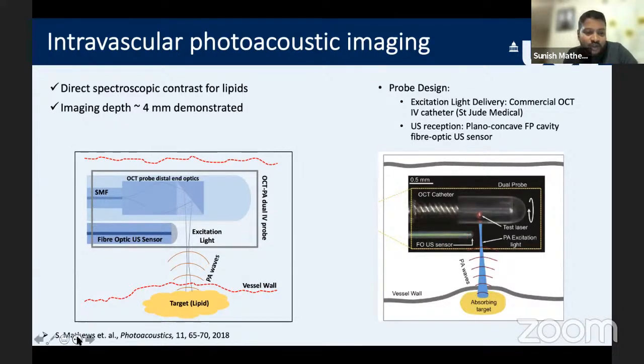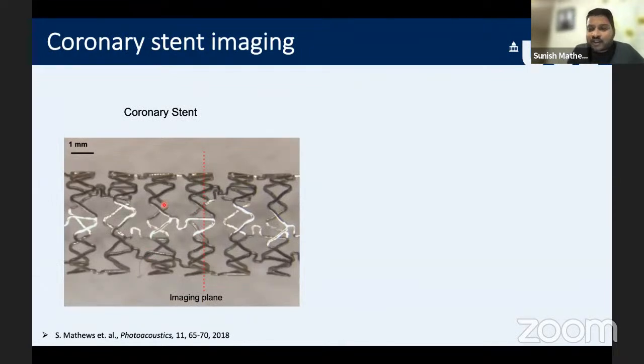Now, let me show you some of the images here. To test our fiber optic probe, we tried to image a coronary stent. This is the image of a coronary stent that is actually implanted inside the artery near the blocked region to make it wider so that the blood flow is normal. These are all part of the surgery. So basically, we just use this to test our imaging probe, how well it can image inside the artery, or just to have an imaging target. It is circumferential or circular in shape. So we put our probe inside somewhere around this region, and we did a circular imaging.